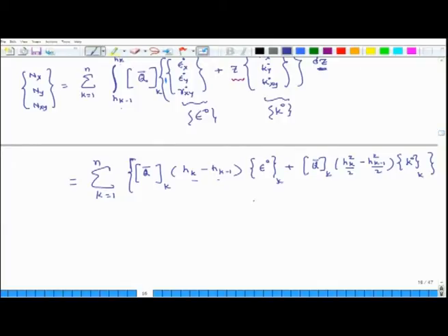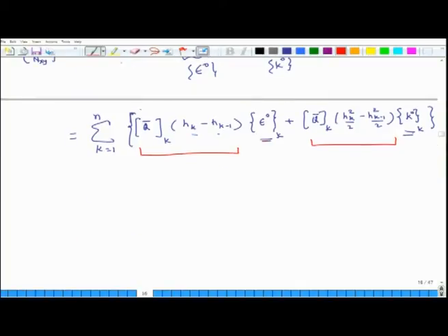Now, across all the layers the midplane strain does not change, because it is the midplane strain. So, essentially, when I am adding this up, I do not have to worry: epsilon naught is common. Same thing in this term, k naught is common. So, I have to add up products of these for individual layers. Okay. So, essentially what I get is, now this is a 3 by 3 matrix and this is just a number.